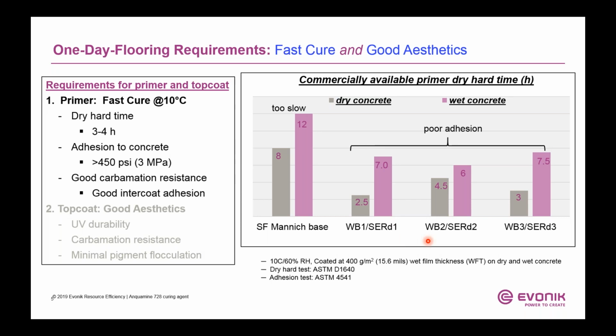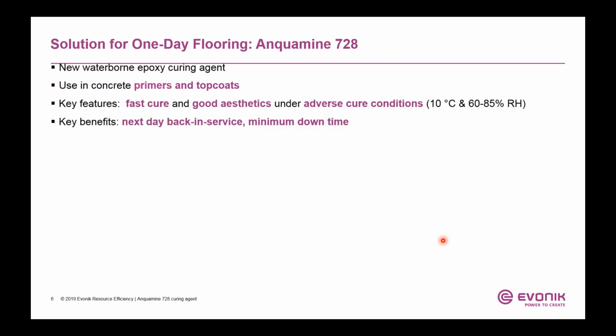For the waterborne systems on dry concrete, it looks like they could meet the requirement for primer. But if we look at the adhesion, all the adhesions are very poor on dry concrete. And on wet concrete, all these systems actually dry much longer, almost double the dry time. So none of these commercially available fast systems deliver for the one-day requirement.